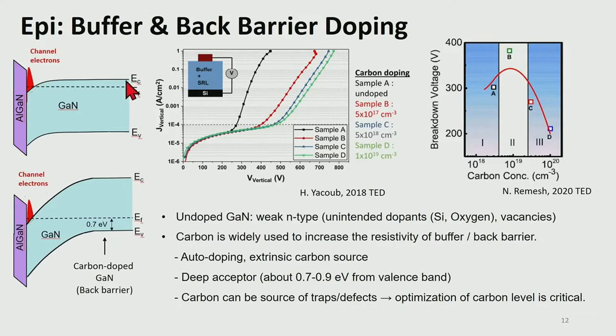So under high voltage stress, the electrons in the channel can spill over to the buffer and cause a large lateral or vertical leakage current. So to compensate the n-type dopant effect, the carbon is mainly used as a deep acceptor. So if you dope the back barrier with the carbon, now the Fermi level is pinned at the carbon level, which is about 0.7 eV from the valence band. So as you can see in this figure, the entire band is raised, which can provide a better charge confinement, so it can reduce the vertical and lateral leakage current.